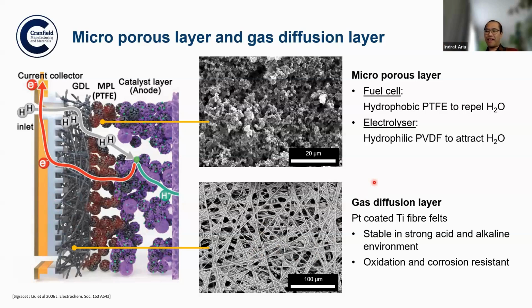Why do we need platinum to coat the titanium fiber? That's because platinum is stable in strong acid or alkaline environment, and it is oxidation and corrosion resistant. Without the platinum, the titanium will get oxidized very quickly. Once it oxidizes, it becomes titanium oxide. Titanium oxide is non-conductive, first of all. And worst of all, it can be corroded. So if you put it on the anode side, the titanium will get corroded very, very quickly. Hence, you need platinum.